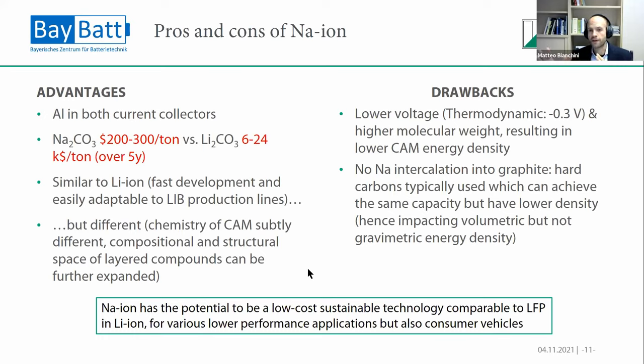There's also some drawbacks, to be fair. Some we can really do nothing about because they're thermodynamics. So we lose about 300 millivolts because of the redox couple of sodium not being as negative as the one of lithium. And also there's a higher molecular weight of sodium. So we're going to lose also some energy density there.